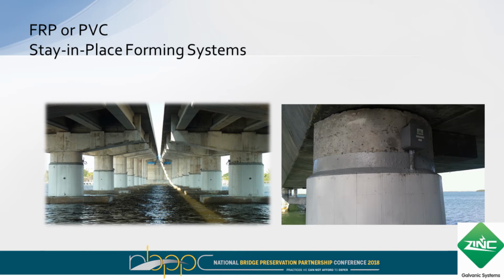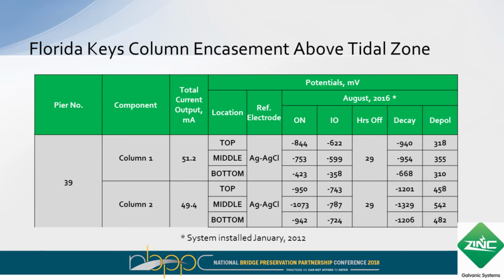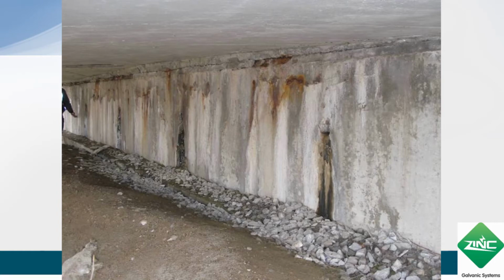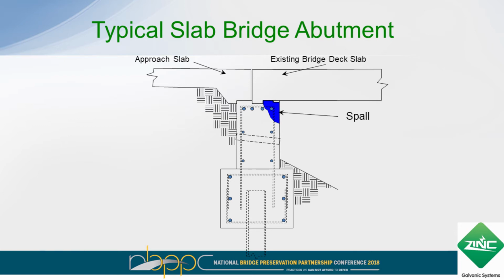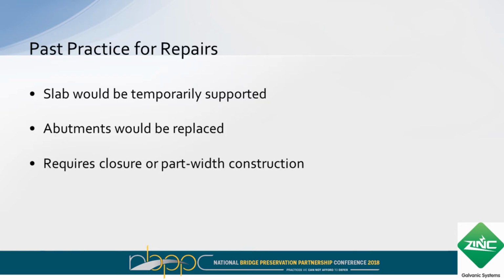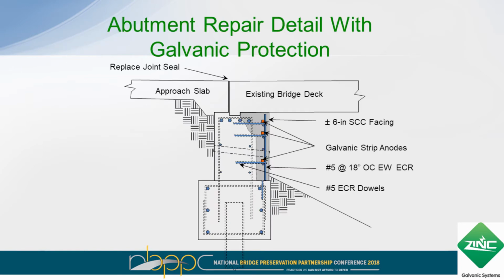This is some data from Florida DOT. This project was installed in 2012, so it's 4.5 years old. And if you understand the corrosion testing, it's getting high levels of polarization and current. The same type of situation with regard to abutment walls, abutment wall repairs. This is Ohio DOT, slab bridges, joints over the abutment wall, spalling. They used to replace the slabs, but that would cause a lot of issues. So the face was expanded, and then distributed anodes are placed within the expanded wall, basically a wall in front of a wall. And you see the anodes placed here.